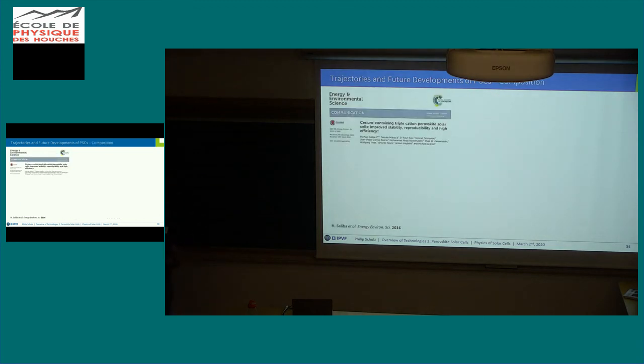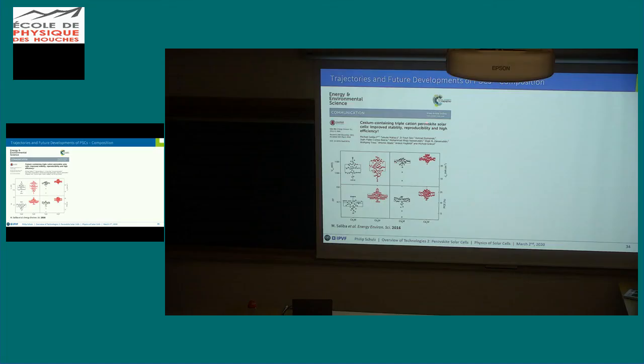In order to run you through the most important milestones, and I'm almost done. It was really the breakthrough by Michael Saliba, while he was in Michael Grätzel's group, to use these cesium-containing triple cation perovskites. And if you remember, I showed you before the Goldschmidt tolerance factor chart. If you use purely formamidinium lead iodide materials, you will see a phase transition from this photoactive alpha phase into the delta phase. Adding cesium brought it into the range of between 0.8 and 1 for the tolerance factor, and made it much more stable,